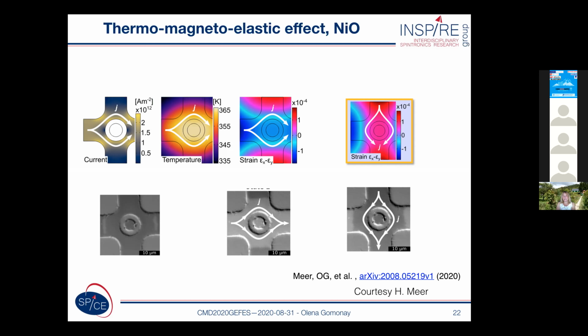Nevertheless, in this case, we still see switching depending on the direction of the current. We see 90 degree switching, which is fully consistent with a thermomagnetoelastic mechanism and could not be explained by other theories, at least known to us.